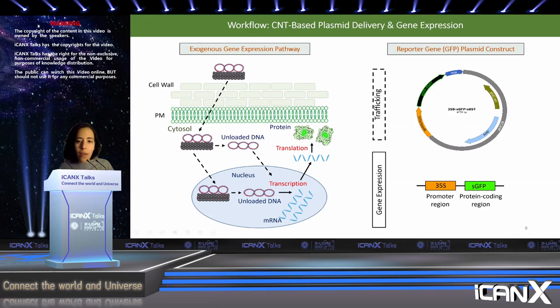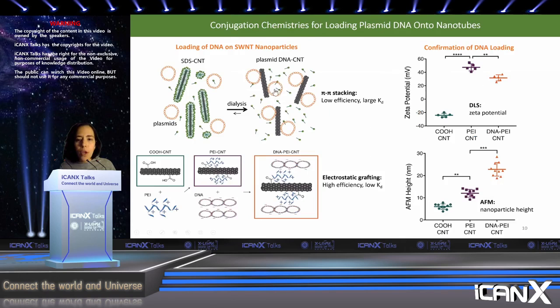In this chemistry that is accomplished through slow dialysis exchange of the surfactant for a plasmid, we can load plasmids onto carbon nanotubes through pi-pi stacking interactions between the aromatic bases of the DNA and the sp2 hybridized carbon lattice of the carbon nanotube. So these are loaded through pi-pi stacking associations, akin in energy to about a hydrogen bond, having a large dissociation constant between the plasmid and the carbon nanotube.